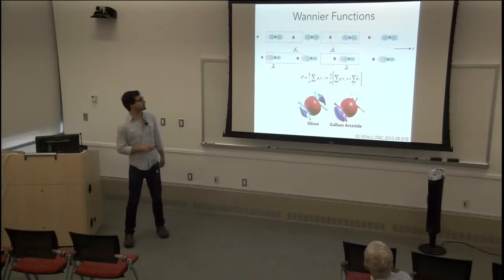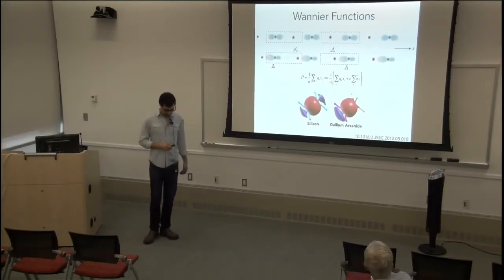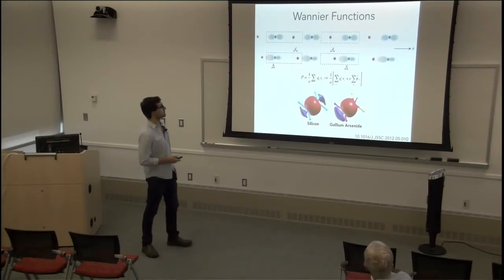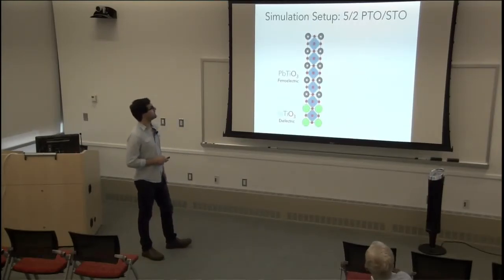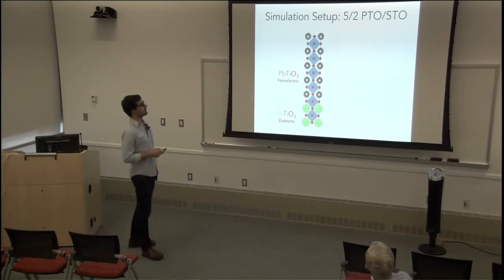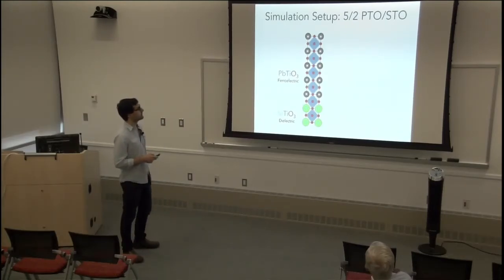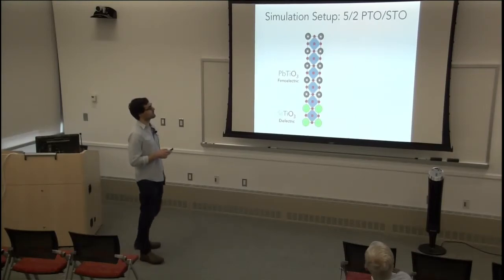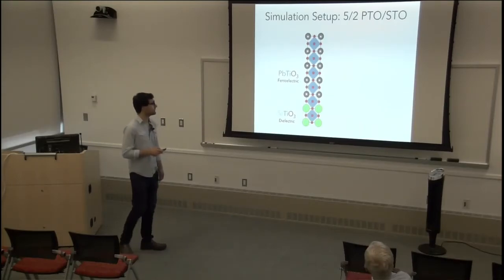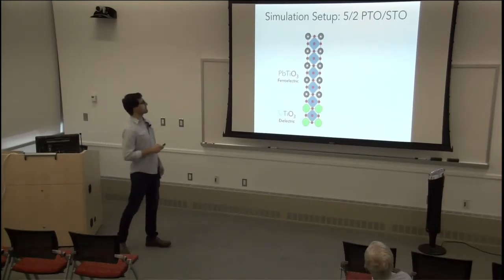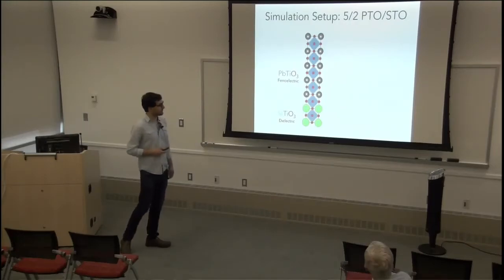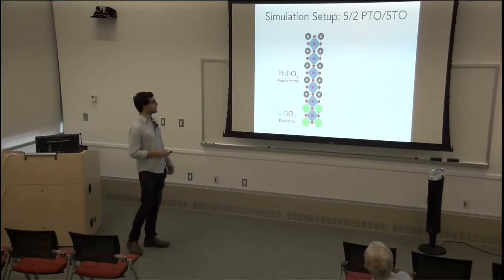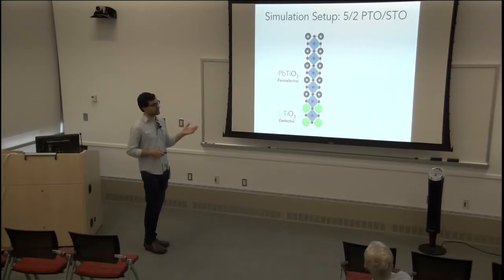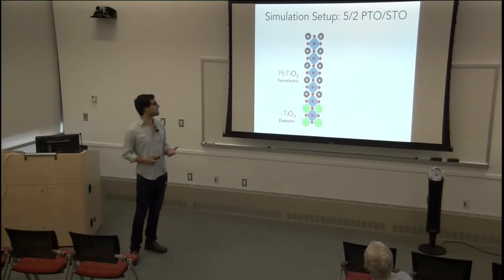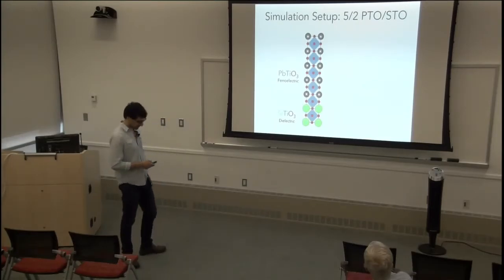Okay, now finishing this detour, let me go back to the actual superlattice. I start with a PTO-STO superlattice, lead titanate, strontium titanate. The case I'm going to talk about is a 5-2 lead titanate, so there are 5 unit cells of lead titanate and 2 unit cells of strontium titanate. Of course, this is the pristine superlattice, so we know it should have a symmetric double well. What do I do to perturb the system to introduce an asymmetry?